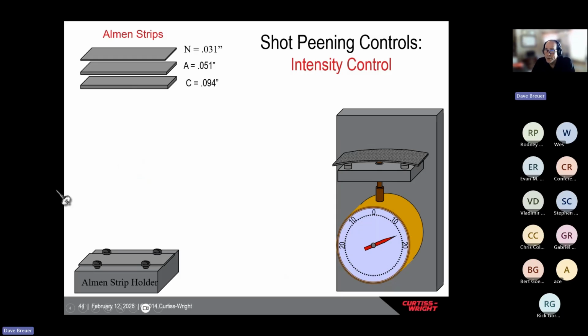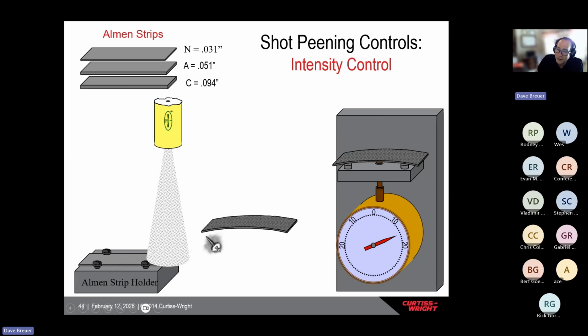When you use almen strips, before you run a load of parts, you process almen strips, and the strip has to be mounted into a block of some sort. It should predictably distort, kind of like forming a mini airplane wing - it will arc towards the shot peening, and we measure that with a dial indicator. Using the A strip, which is the most common - a 50 thousandths thick strip - if it shows 15 thousandths, we'd call that a 15 thousandths A intensity.